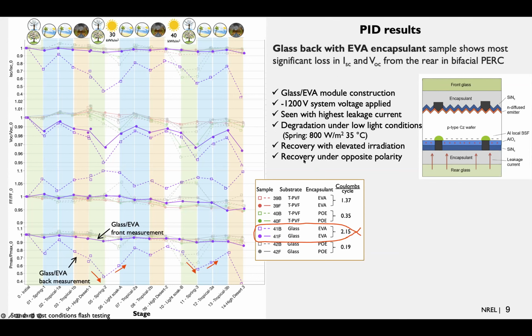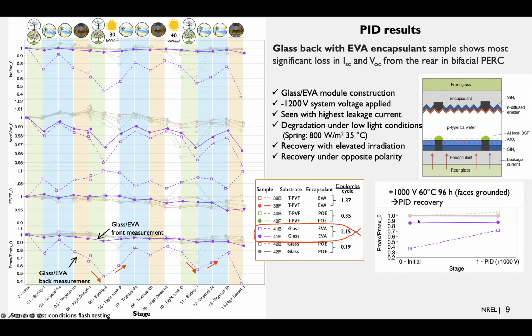And there was recovery with elevated irradiation. So for example, when we take the modules out for diagnostics and put them under sun, we saw recovery. But also here, when we went from the spring, which has low light, to the tropical, which is higher temperature and full sun irradiance, we actually also see recovery. So this, and also this final point here, recovery under opposite polarity.